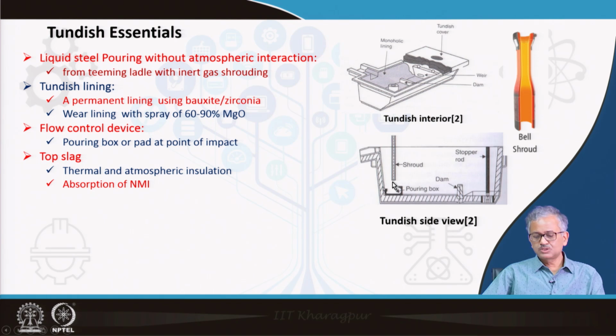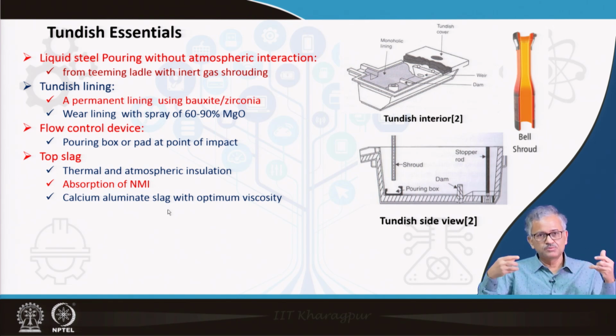Then absorption of NMI: this top slag also acts as an absorber for the non-metallic inclusions. When the inclusions float to the top of the tundish, they should be absorbed by the slag. So the slag property should be sufficient that it can immediately absorb whatever inclusions come to the top. Basically a calcium aluminate slag with optimum viscosity is used, because if it is too viscous or too fluid, it is not good. It will also have other properties like favorable surface tension with the inclusion such that it can engulf the inclusion into it.